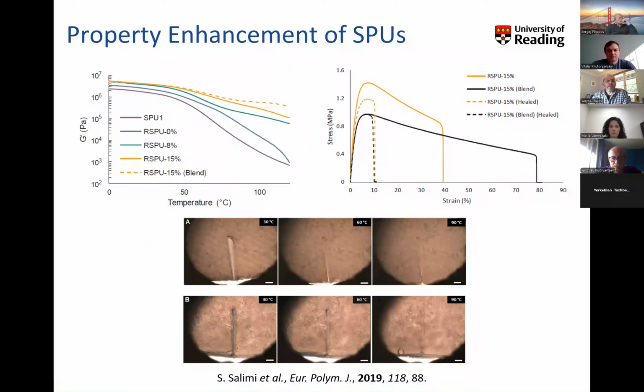And what we've found is that you can get quite significant enhancements in the storage modulus by simply retaining that low molecular weight additive within the bulk polymer, but it comes at a consequence: you increase the Young's modulus, but you tend to lose out in terms of their elastic characteristics. But these materials are also healable. At 90 degrees C, you've healed the material completely.